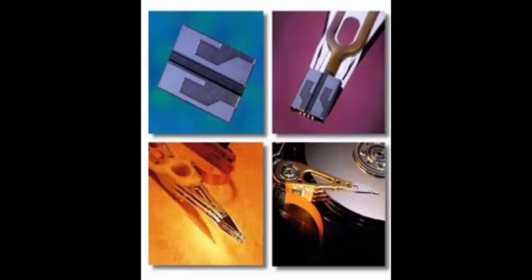When we come to the present applications, the basic one is magnetic recording heads. The magnetic heads which are used in hard disk drives are used to read and write data into the hard disk. ALD aluminum oxide has been used in gap layers since 2000. A thin conformal insulating film is needed, and ALD saved the life of the whole technology.